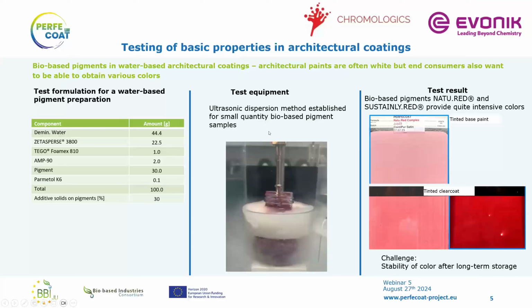But we managed to prepare this version, and they were giving a good performance in terms of particle size. And then we tested them in a base paint and also in clear coats, as you can see in the drawdown on the right, with different pigments from Chromologics, NATU.RED®, and they also tested the Sustainly Red. So you can see a very nice tinting strength, which is a great result in both. The only thing to work on further is to improve the color stability long term with the exposure to light. That's still a point to improve a little bit.